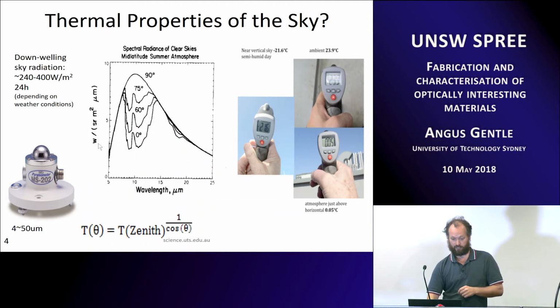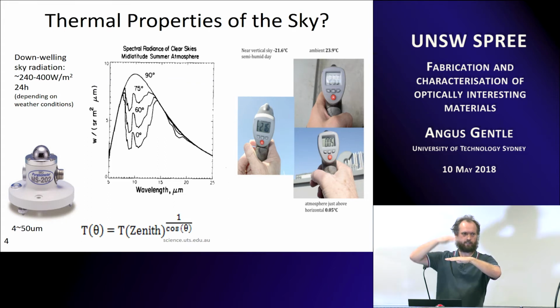And that's basically because straight up, it's relatively transparent. You don't get much radiation coming in, apart from that CO2 bump. As you go to higher angles, you're getting more and more radiation coming in because it's less transparent. You also get this other thing that when you start off at ground level, the air temperature drops off at a lapse rate of 7 degrees per kilometre as you go up.